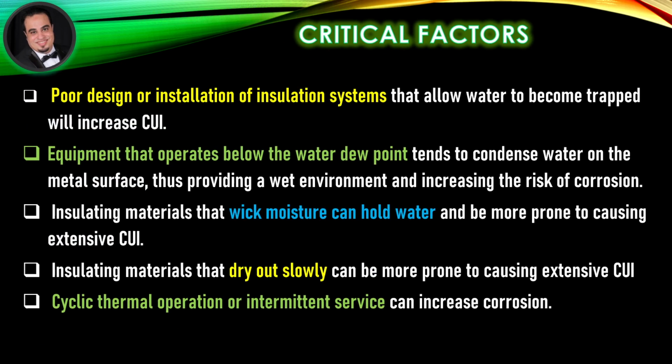Poor design or installation of insulation systems that allow water to become trapped will increase corrosion under insulation. Equipment that operates below the water dew point tends to condense water on the metal surface, thus providing a wet environment and increasing the risk of corrosion.